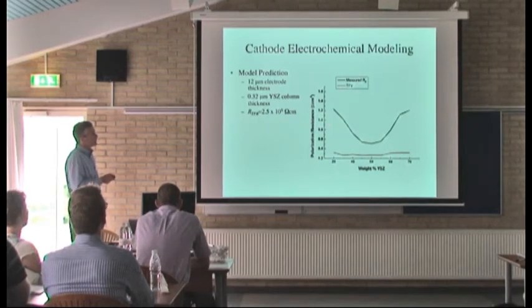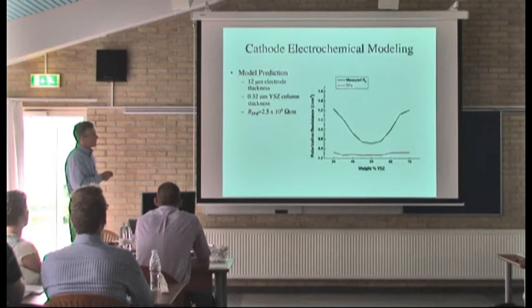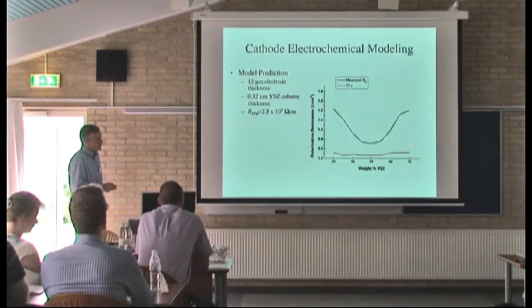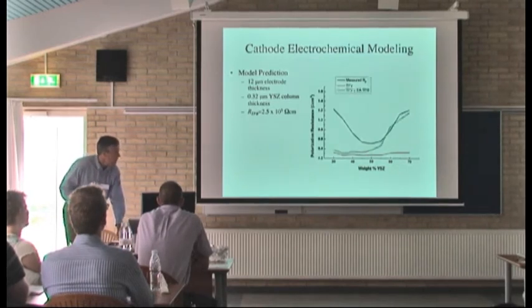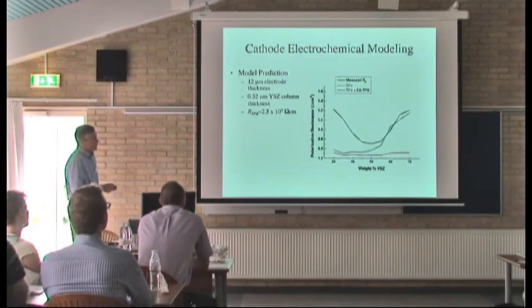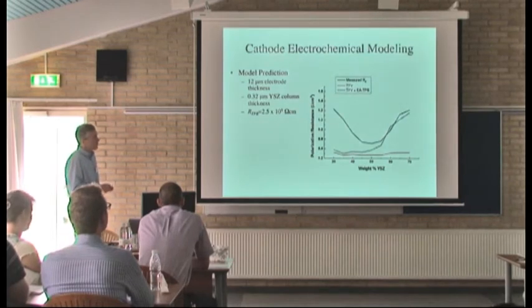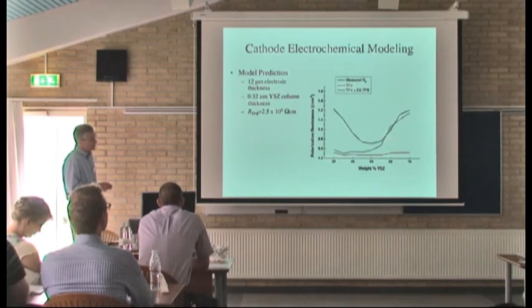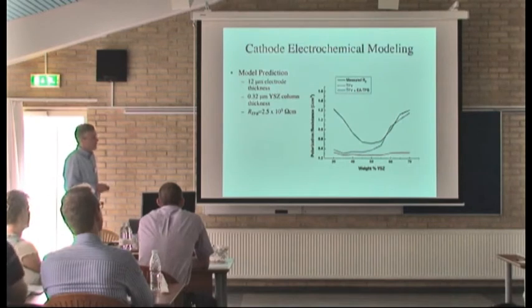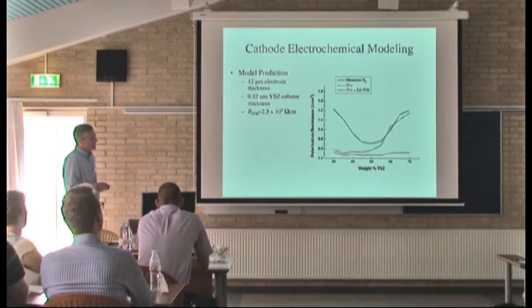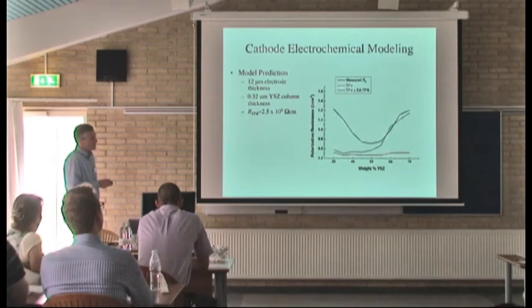If we just did that naively and tried to predict the polarization resistance using literature values for the resistance of the TPBs in LSM-YSZ, we get something that doesn't really match the observed variation at all. Then we figured out to look at the connectivity effects. The blue curve now looks not at all TPBs, but only at connected TPBs where all three phases of the TPB are contiguous. We see that, at least on the LSM-rich side, we're getting a match to the data. Interestingly, we see very good connectivity even in the YSZ phase down to very low YSZ content, which we didn't see for the LSM phase.